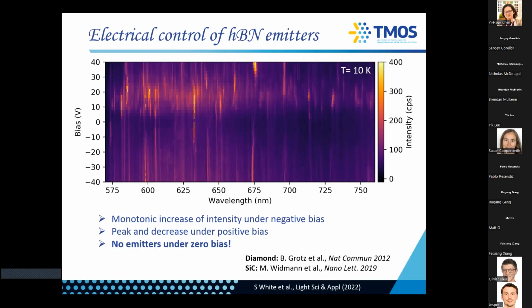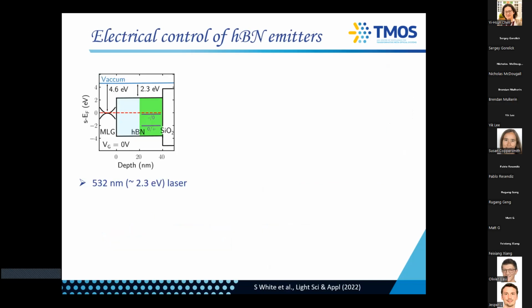So how do we explain that? To explain that, we can draw a proper level diagram. So this is kind of the level structure of the device. So we have about 4.6 eV to the vacuum from the graphene level here, and we have two charge transition levels of the emitters and the Fermi level of the junction.